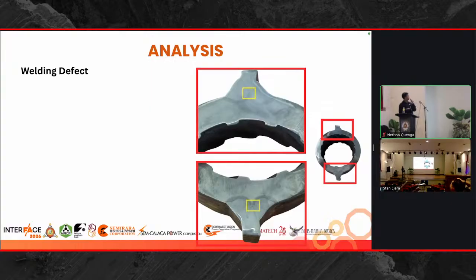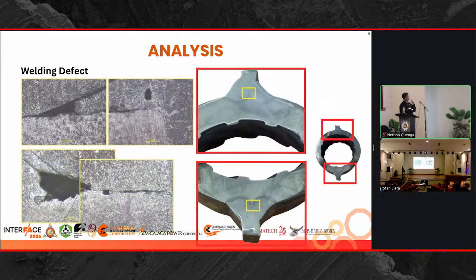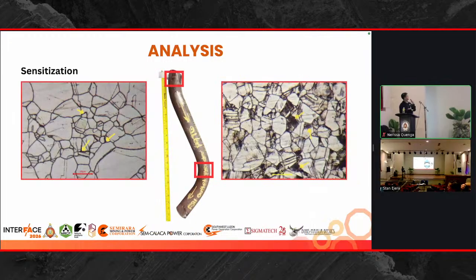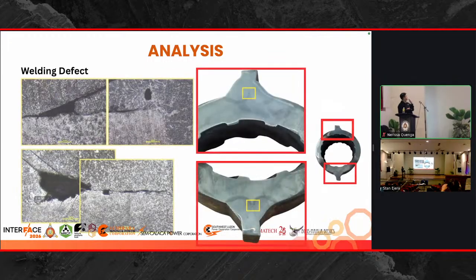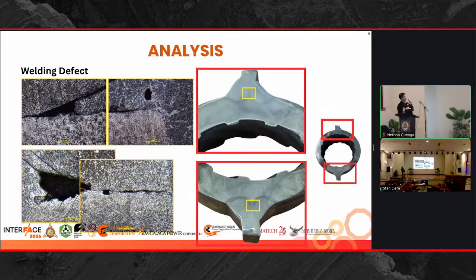But when we get the microstructure at this point, it was revealed that at this interface there is a void. This void cannot really be seen with the naked eye, and can only be seen when we observe the microstructure. We can see that there's a lack of penetration, even though it is very small, between the interface. So it says a lot about the quality of welding applied in this part.